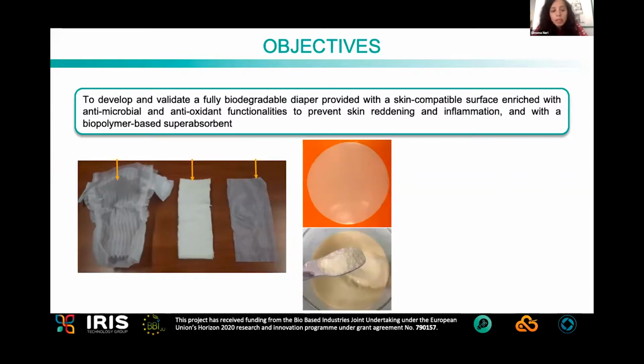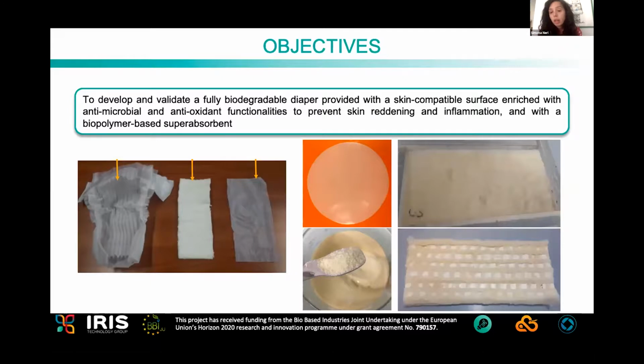After that, we moved our attention to the super absorbent polymer. We achieved bio-based and biodegradable polymers just by modifying cellulose, and in particular we moved to carboxymethylated cellulose. In this case, we also demonstrated that you can obtain this polymer from recycled cardboard, which I think is also a nice result. Here you can see how we produce our super absorbent core. We used a cotton substrate in which we were able to impregnate the super absorbent polymer.